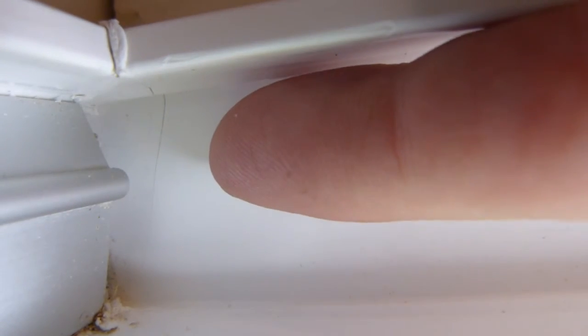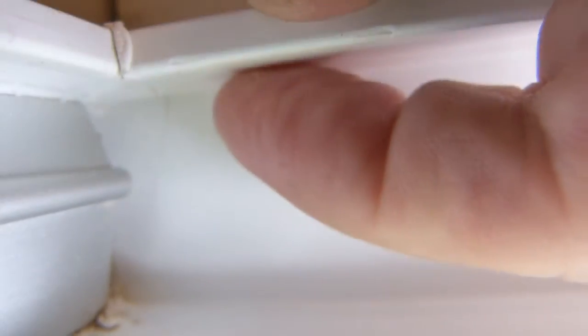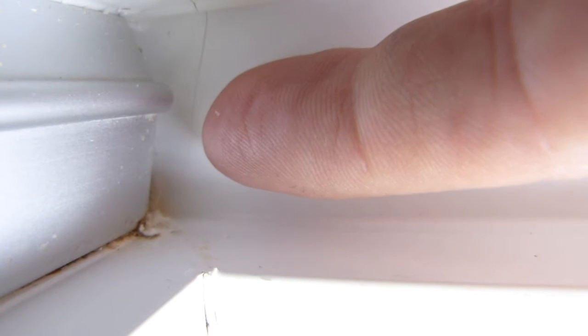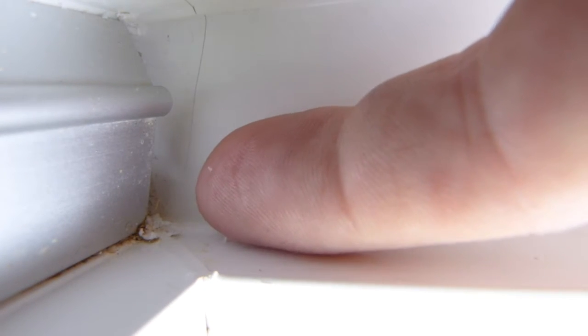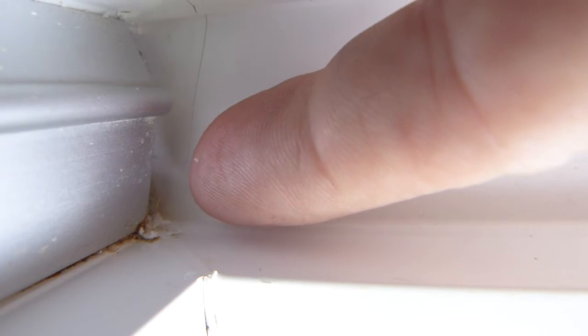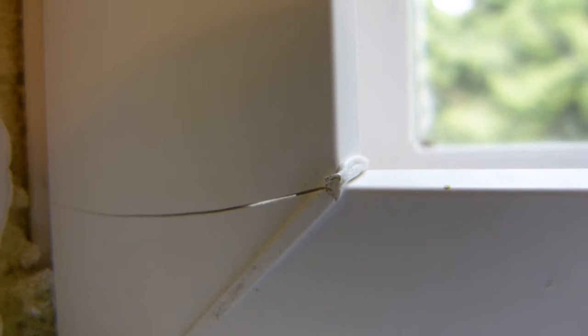Let's have another look at this crack from this side. Let me just set up the camera here. So you can see there on the inside, that this plastic part is cracked through its entire thickness, and the crack continues on this part of the frame there, tapering to ever narrower and narrower, and it stops short of the other mitered corner there. So that's how this looks. There's no sign of surface impact, no chipping, no denting, no abrasion, no scuff marks, nothing else, just a single crack.